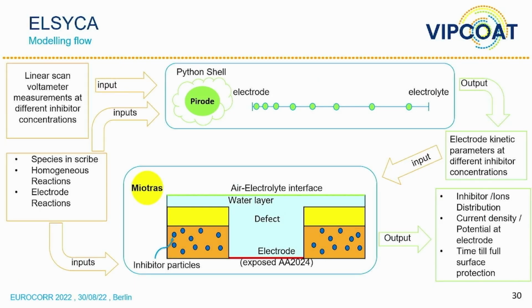The last part, at the moment, is the VIPCOAT project. This is a Horizon project where Axalta and Airbus are also partners, and it is led by Hereon in Germany. Our part is to come up with a finite element model that predicts the corrosion protection in a defect. Others are focusing on the inhibitor selection and also on the transport and the leaching of the inhibitor in the coating. But our part is to have a finite element model of what is happening in the defect. So here you see, this is done with Elsyca.